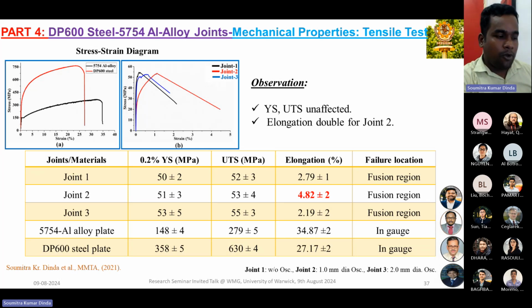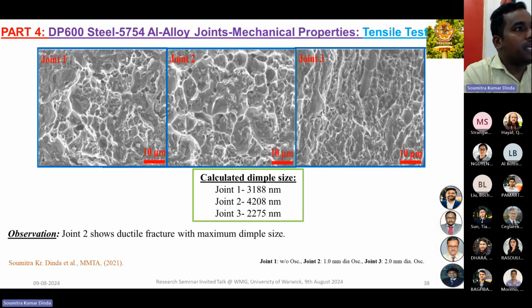This is because of the formation of intermetallics. So we did the fractography study, and we calculated the dimple size. As you know, if the average dimple size is big, that means the chances of ductile mode fracture will be more. In the case of joint 3, we are getting the lowest dimple size, 2275 nanometer, and the highest for joint 2. That's why joint 2 gives the maximum elongation percentage before going to fracture.